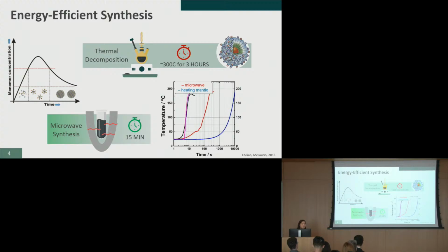In addition, with microwave synthesis, we can change the power, the pressure, and the temperature at which we make particles. And that's really great for optimizing nanocrystals to different energy-saving reactions. So as you can see, the red line, which represents microwave synthesis, is able to reach the same exact temperature as traditional heating mantle synthesis at exponentially lower times. Sometimes these reactions can happen in mere seconds.